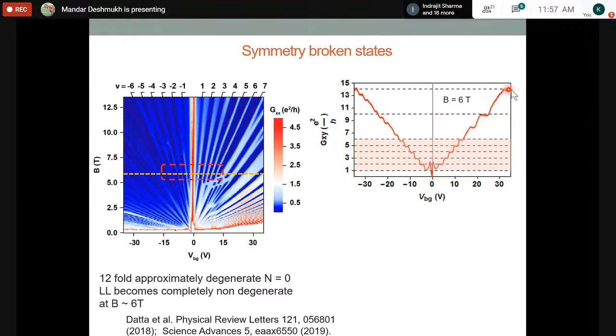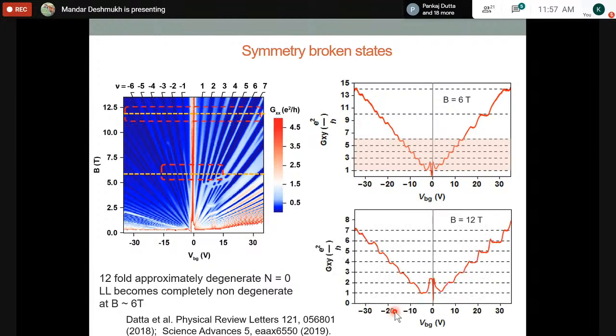Sometimes you'll see a step of 2 or 1 here, and then here you'll see a step of 2, and then here you'll see a step of 4. And the magnitude of the steps tells you about the degeneracy, how degenerate the individual Landau level is, whether it is degenerate with 1 or 2 or 4. That provides information about what's going on in the electronic system. Here, for example, at large magnetic field, you'll see that degeneracy is completely lifted and GXY is in units of 1 e squared over h.